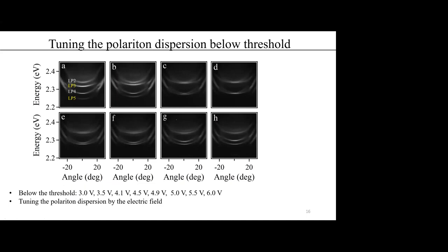The external voltage applied across the microcavity can tune the polariton modes both below and above threshold by controlling the orientation of the liquid crystal molecular director. This graph shows the dispersion of the microcavity as a function of the external voltage below threshold. We can observe clearly Rabi splitting when the voltage is 3 volts. Increasing the voltage will move the horizontally linear polarized lower branch polariton branches, where the vertically linear polarized polariton branches are fixed. So the energy difference between these two sets of modes is decreased, showing the same behavior as the cavity modes in our Science paper.